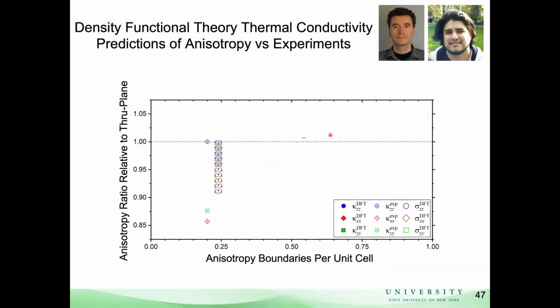And so next we want to compare the anisotropy ratio that we measured experimentally to the anisotropy ratio that Alexei and Ernesto simulated with DFT. So this is our experimental anisotropy. Each one of these colors represents an anisotropy in a different direction, normalized by the Z conductivity. For the experiment, we had anisotropy of about 15%. The simulations had a similar degree of anisotropy, about 15% or 10%, depending on the orientation.